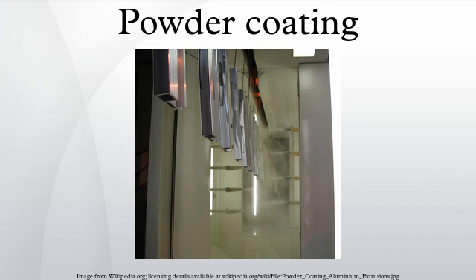Properties of powder coating: because powder coating does not have a liquid carrier, it can produce thicker coatings than conventional liquid coatings without running or sagging, and powder coating produces minimal appearance differences between horizontally coated surfaces and vertically coated surfaces. Because no carrier fluid evaporates away, the coating process emits few volatile organic compounds. Finally, several powder colors can be applied before curing them all together, allowing color blending and bleed special effects in a single layer. While it is relatively easy to apply thick coatings which cure to smooth, texture-free coating, it is not as easy to apply smooth thin films.